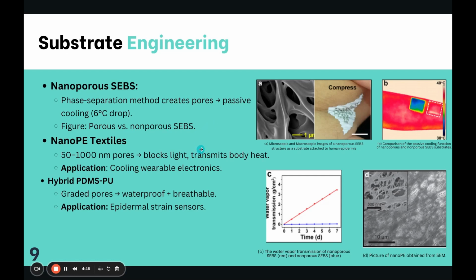Then comes nano-PE textiles, nanoporous polyethylene. It's a textile with thermal comfort and has pore size of 50 to 1000 nanometers, and it blocks visible light, transmits body heat, and it feels like fabric. And it gives a cooling effect up to 2.7 degrees Celsius cooler than cotton. Then we have hybrid substrates, which include both nanoporous PDMS and silica nanoparticles. It gives passive skin cooling plus a waterproof layer. The temperature drop is 2 degrees Celsius over bare skin, and it is also used in stretchable and breathable sensors.